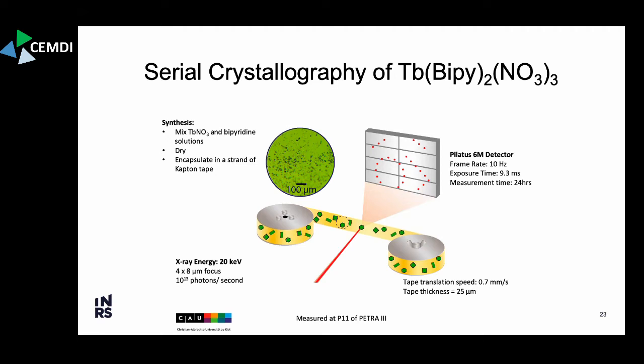Here's a setup for an experiment I did at Petra 3, which is a synchrotron in Germany. And we had a powder of terbium bipyridine nitrate. We sandwiched it between two pieces of Kapton tape, and then we just ran the tape, just like a cassette drive, basically, and rapidly took diffraction patterns of whatever was in the beam at that time. So here's a movie of the data stream coming in. You can already see the heterogeneity that you get when you make these sorts of measurements.